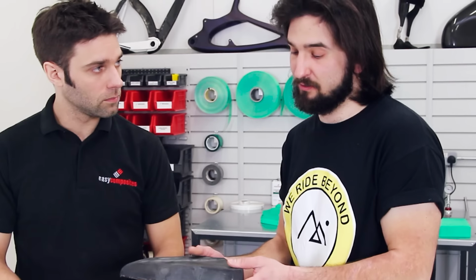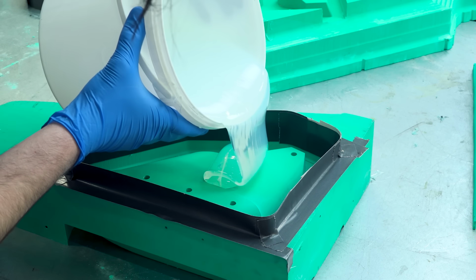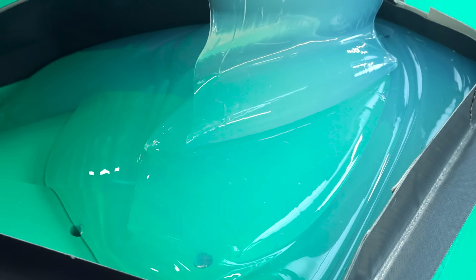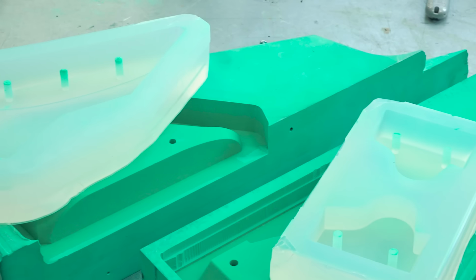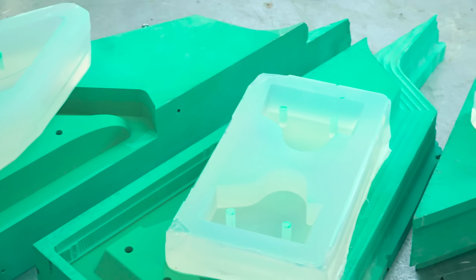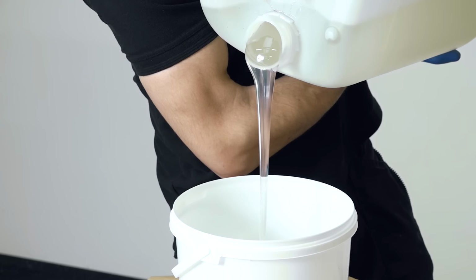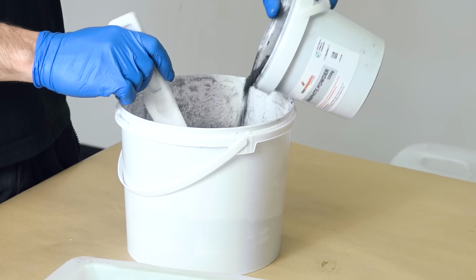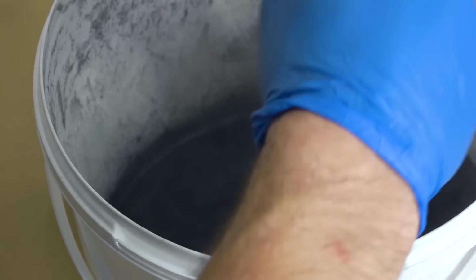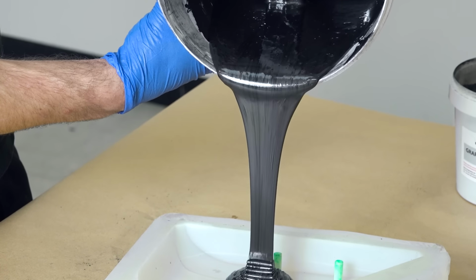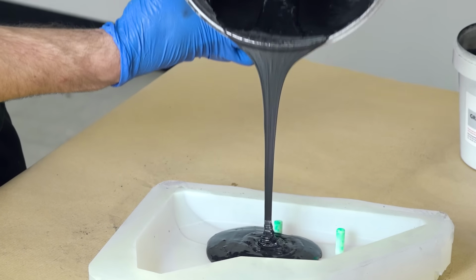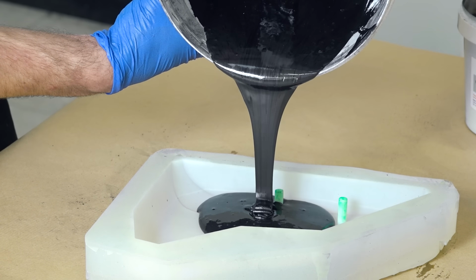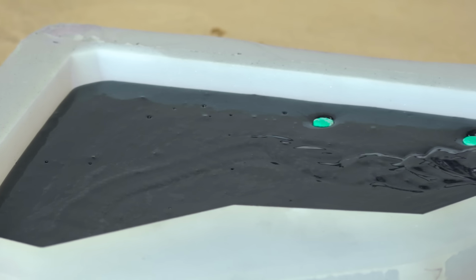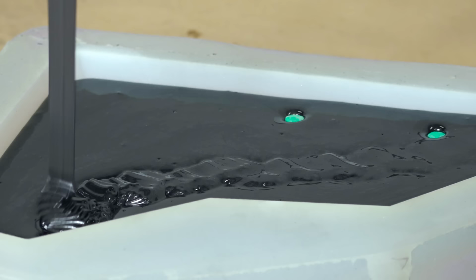So basically, I machine patterns from epoxy, an epoxy motherboard, and then I cast silicone over this motherboard. You made a negative from silicone. Yes, and from this negative, I use high temperature resin and graphite powder, to give it some strength. And I've cast the inserts into those silicone molds. Right, so you just poured the resin into the silicon molds to make that insert.